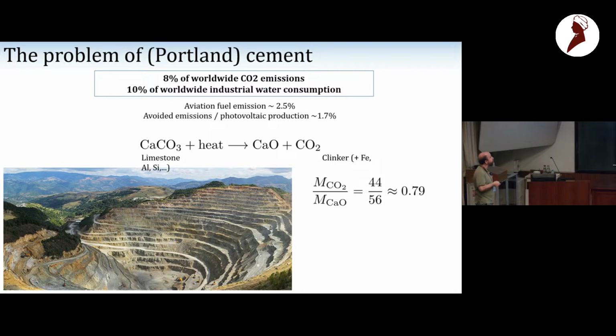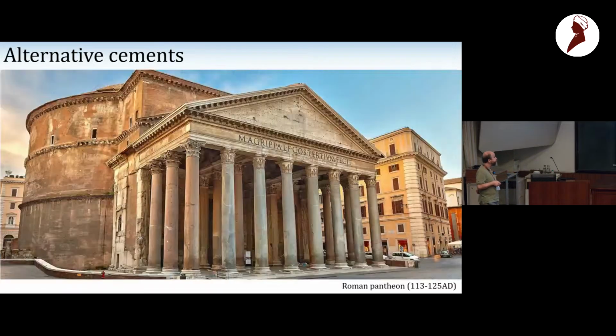And the reason why it's 8%, and it's 10% of worldwide industrial water consumption, which is another tremendous environmental issue, is that the main way to make cement is to use a limestone that you heat. Simply, it's chemistry. You just burn limestone and you have CaO plus CO2, and just by the chemical balance, you see that for 1 ton of cement, you produce 0.7, 0.8 tons of CO2. And that's not counting the heat.